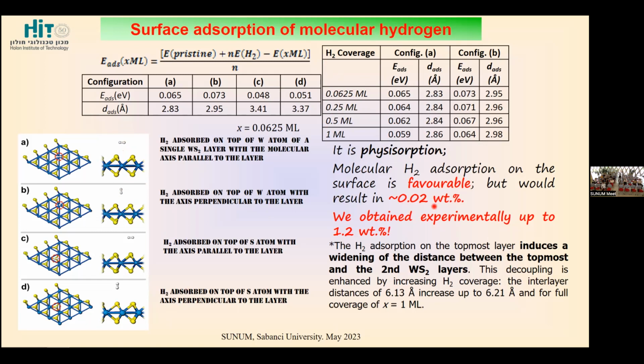The problem is that if we have only physisorption, we would have only 0.02 weight percent. Experimentally, we obtained much better. So it's good that we started our study from experiment and from theory, because theory was quite discouraging. And for experiments, we had 1.2 weight percent, so we have to consider some more configurations other than just physisorption.